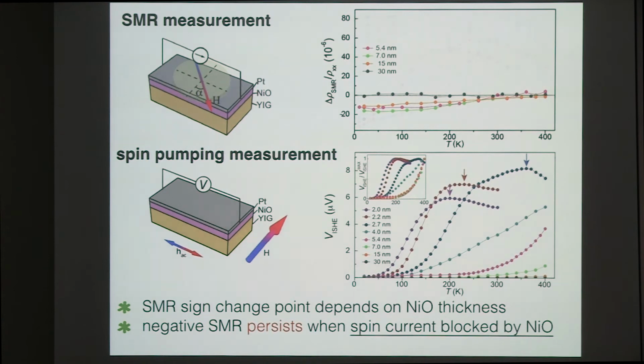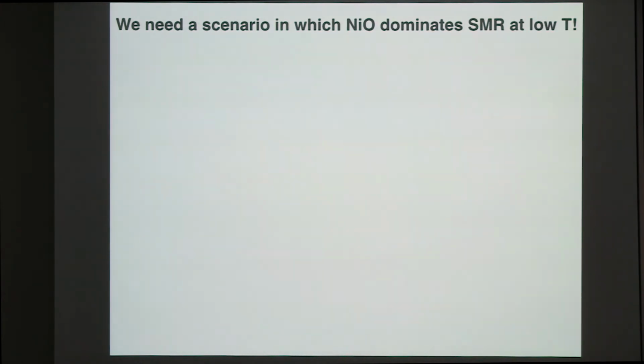All these things tell us we need a scenario in which SMR can be dominated by nickel oxide only, because you don't need YIG actually. But it has to be said that it seems you need the YIG for the alignment of nickel oxide, but you don't need the YIG to feel the spin transmission through nickel oxide.